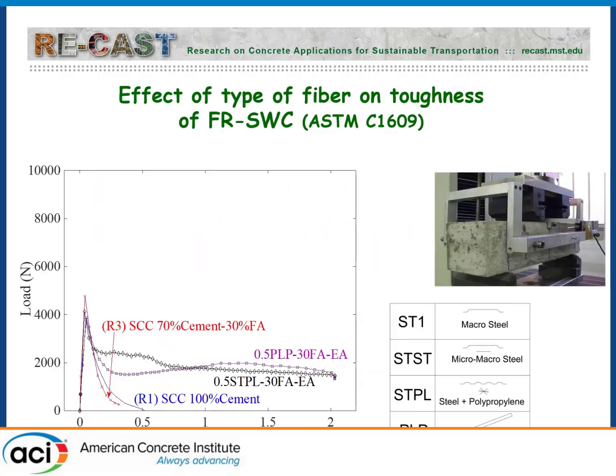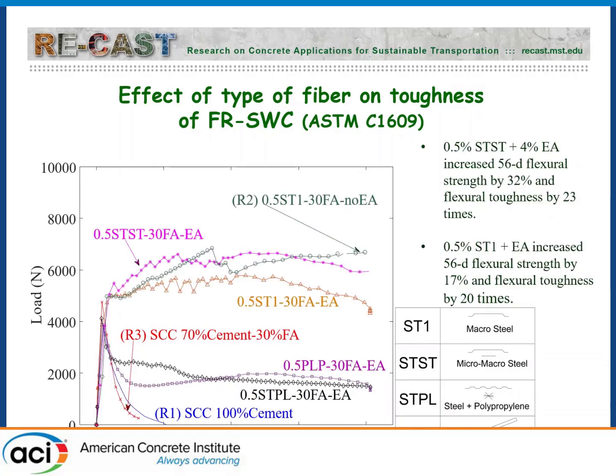So if you look at the performance, in this case 4-point bending of fiber reinforced concrete, in blue over here is the SCC without any fibers. As expected, you reach the peak and then you lose ductility. The polypropylene fibers, as expected, also lose a lot of ductility, but give you good residual strength at very high deformation. But the performance we're really looking for is this performance. The top three figures are all with steel fibers, whether it's only the 0.5% single steel fiber or the 0.5% combination of micro-macro. You can see that the performance is very good, elastoplastic, a lot of ductility, and you want that in your bridge deck because eventually it will crack, and you want the load carrying capacity to be maintained.